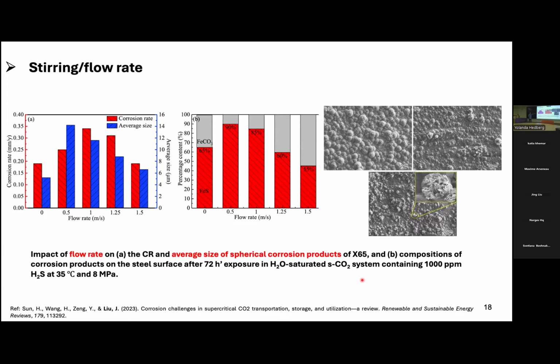Same for this one, then we try to look at the cross section to see what the corrosion layer looks like. You notice that this pattern also agreed with iron sulfide contents. So the conclusion is it's not that simple. It can always be explained by the corrosion product layer, the quality of the corrosion product layer, but it doesn't have one unified conclusion yet. And I didn't show much, but there are lots of diverse results.